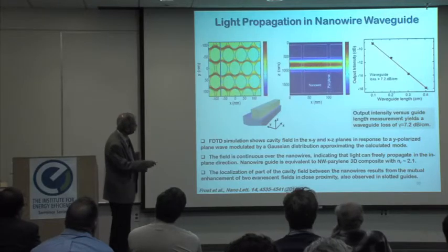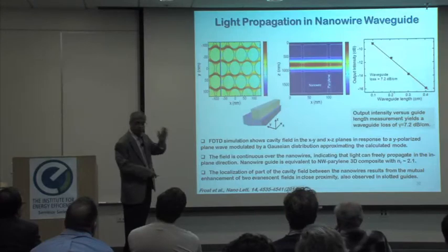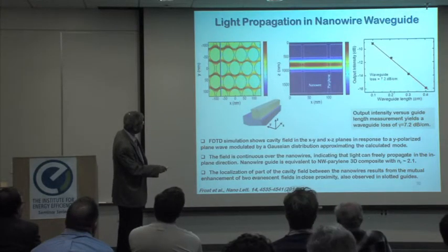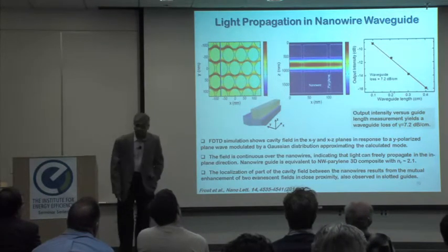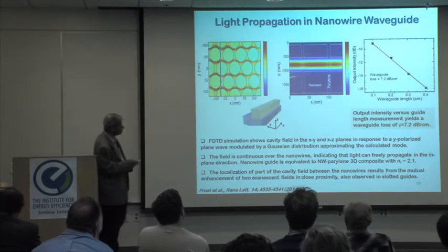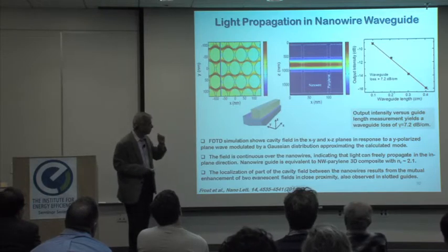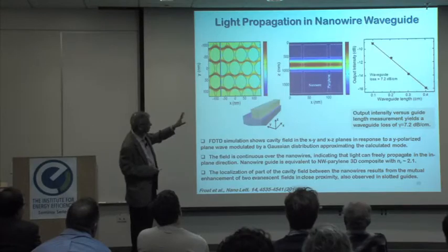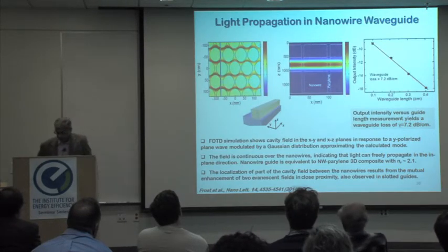And just to be sure, we made waveguides and did a waveguide loss measurement by measuring the transmission along different lengths, and we measured a loss which is very respectable, about 7 dB per centimeter. And in the waveguide structures, of course, we didn't do any p-type doping, and we left out the InGaN discs, and we end-fire it with green light, with 532 nanometer light.